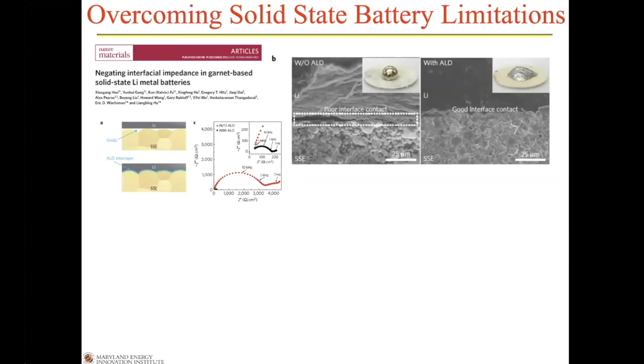And you can see the SEMs of the interface where in fact you can see the gaps that occur. So if I'm doing a macroscopic current density, really the microscopic current density at the points of contact is much higher, dependent upon the actual interfacial contact that we have. We developed a simple atomic layer deposition technique. In this case it was just alumina. And by putting about 5 nanometer thick alumina across it, you can see on the figure on the right how in fact lithium metal now wets, and we get a conformal coating of lithium across all the surface non-uniformities.